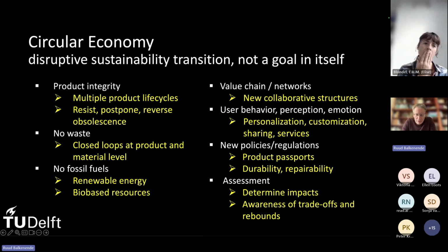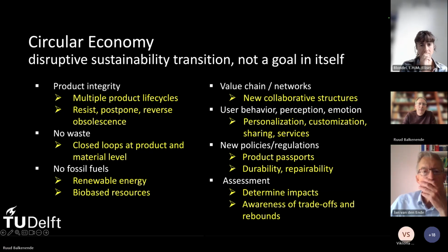But further, when we talk about compost, a large part of the material goes to carbon dioxide and water, and what remains is the minerals and the fibers, and those are fertilizers to the ground. But if you have PLA, that is a completely processed plastic. It doesn't contain any minerals, it doesn't contain any fibers. So it just decomposes completely to CO2 and water and leaves nothing that is beneficial for the soil.